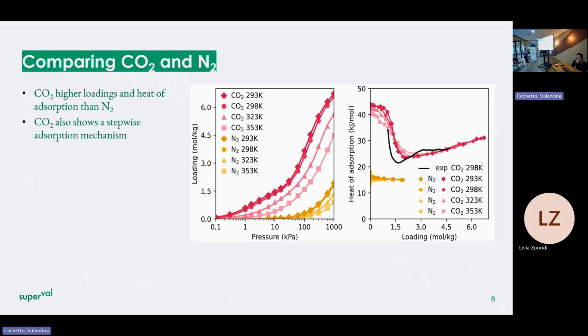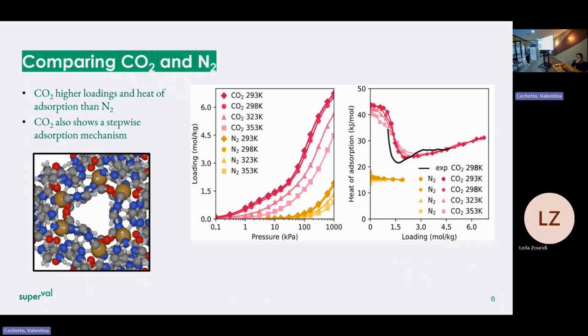Well, we have visualizations of the simulation, so we can clearly see where the CO2 goes in the framework. And what we found is that there are these copper 2+ atoms in the MOF. They are aligned in triangles. So yeah, it's a bit difficult to see in this MOF, but they're triangles, and they provide very confined space in the MOF with an electrostatic potential that is very favorable for CO2 to preferentially absorb.